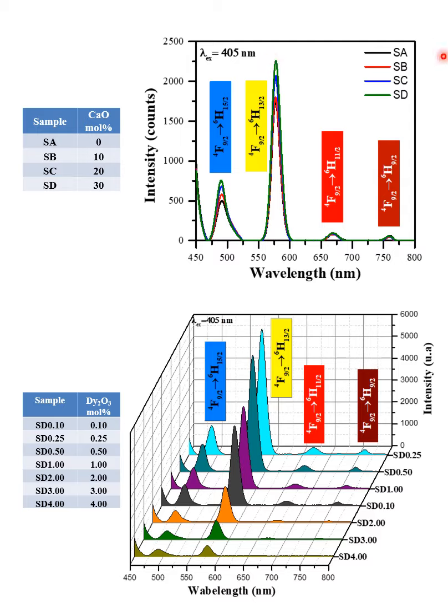with the highest intensity. On the other hand, it is observed that the sample with the lowest luminescent intensity corresponds to the glass with 4% of the dopant. With reducing the doping, the luminescence increases until reaching a maximum value for the sample with 0.25%.